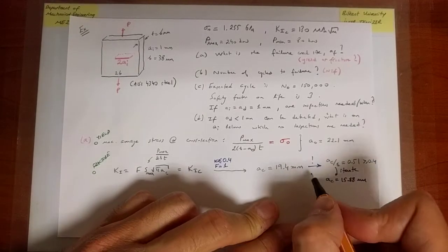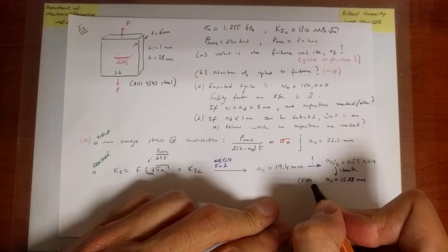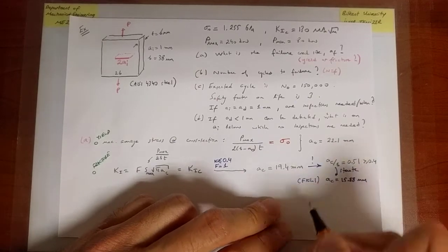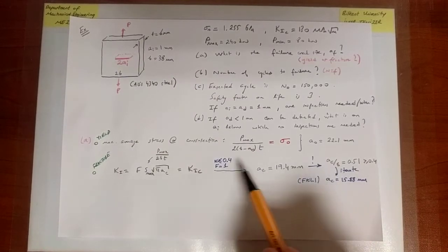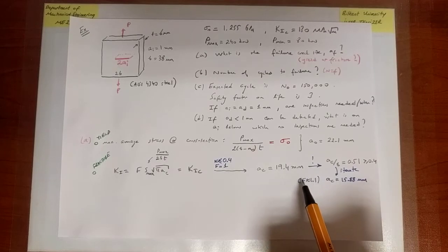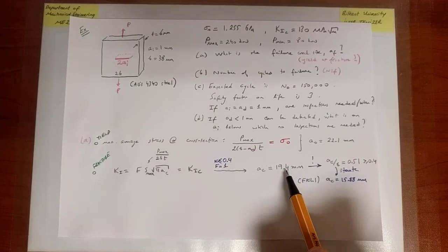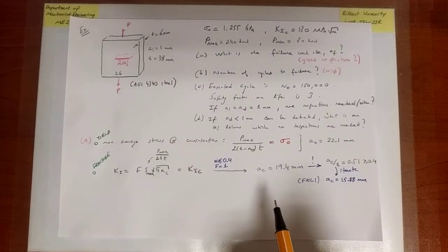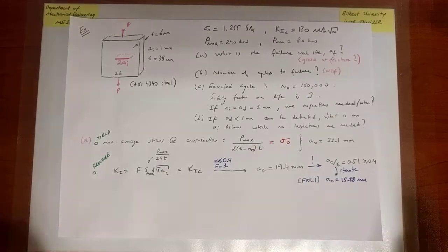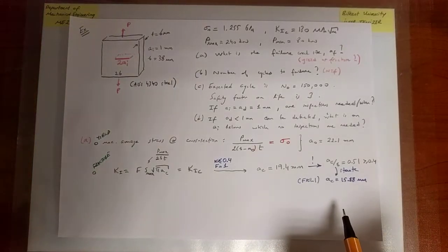At this value of AC, F comes out, interestingly, very close to the 10% bound. Okay, but that's not something that disturbs us. The 10% approximation takes F to be 1 and predicts that. The actual value, it turns out, corresponds to F equals 1.1, and with that, the value of AC comes out to be 15.88. So that's the final result.